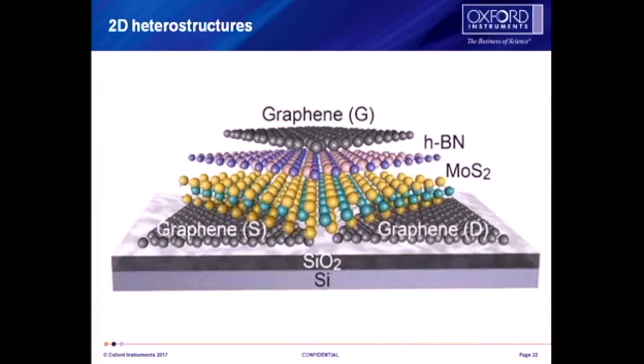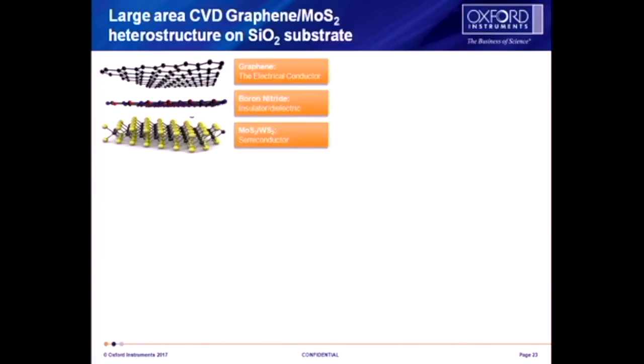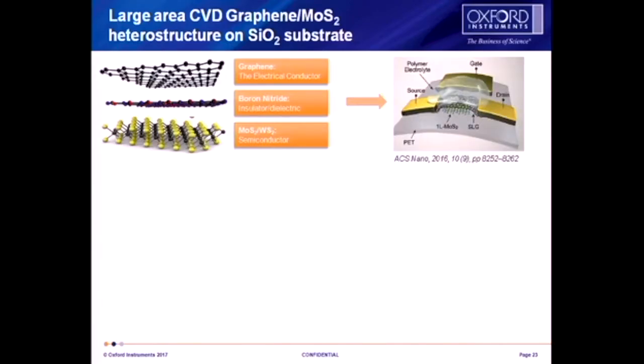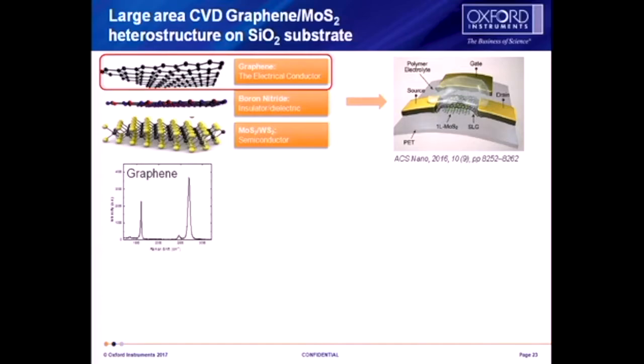Of course, then, what do you do? You've got to put them together to try and make an active device, put some heterostructures together, which is what we've started to look at, very much so. You could see a graphene, a boron nitride and a molybdenum disulfide might make some sort of device. What we've looked at is depositing graphene, then exfoliating it and putting that onto a silicon oxide carrier wafer, and then putting that back into the process system, and then growing molybdenum disulfide on top.